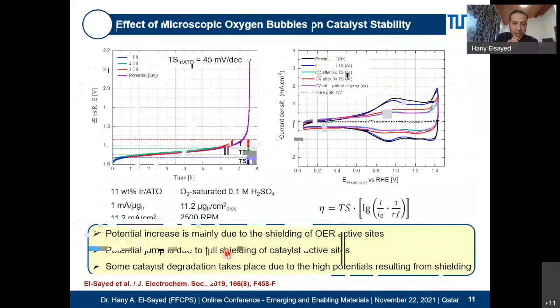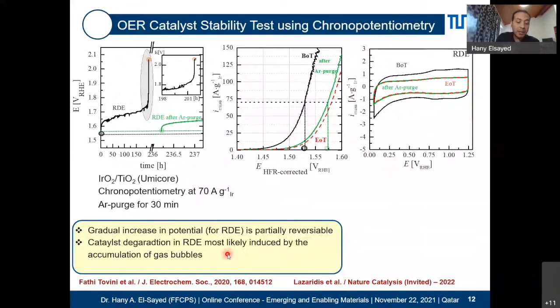Well, let me just go to the second study, which is still very related. In our first paper, when we published it, we were criticized that we did the work using our own homemade catalyst, and this catalyst maybe has some issues. So what we decided to do was a comparison between RDE and MEA configuration, which is basically everything you can use in literature. And not only this, we didn't use our Ir/ATO catalyst, but we used a commercial benchmark catalyst from a company called Umicore, which is iridium oxide on titanium oxide.